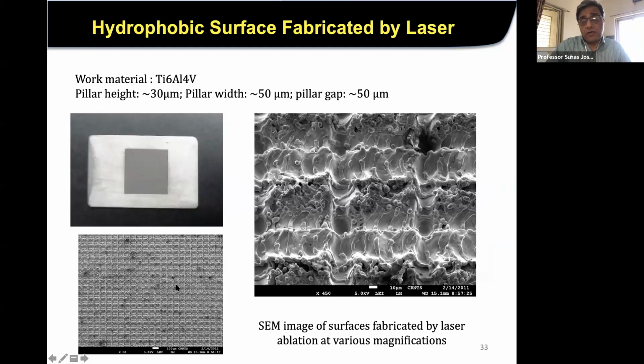This is again another thing. In the first exploration, somebody wanted to know whether you can do it by laser. So this is the enlarged view of laser: this is one line of laser, and this is another line of laser, and this is the pillar which is formed. Each pillar formed here has laser lines from one side to the other. These are very early experiments, but the globules of material on the pillars were actually helpful, and the contact angle was 123 degrees in the case of the laser surface. In the EDM surface it is 114, and the flat surface is 52 degrees.